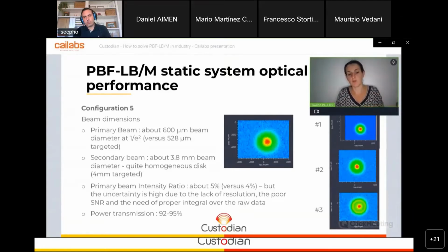The secondary beam was also very close to the diameter that we were targeting in that case, and we managed to have a very good energy ratio in between both shapes. So the transmission of the system was pretty good, more than 90%. So you can see also that the other static systems were managing the needs of changing the dimension of the secondary beam to try different options.